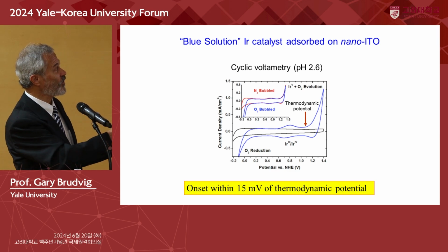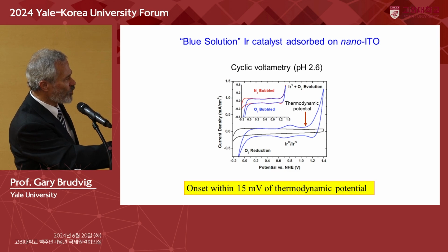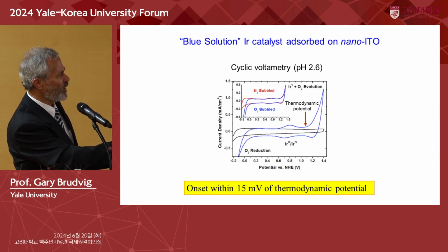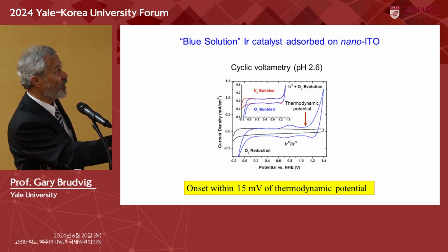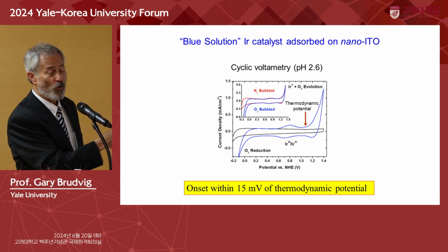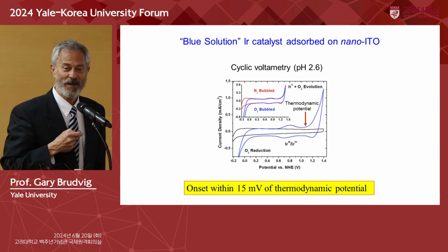And just to take you through this blue trace here, we see a reversible oxidation, which is an iridium 3 to 4 oxidation, followed by onset of catalysis, which shows this jump in current that happens essentially right at the thermodynamic potential. Now, what does that mean?